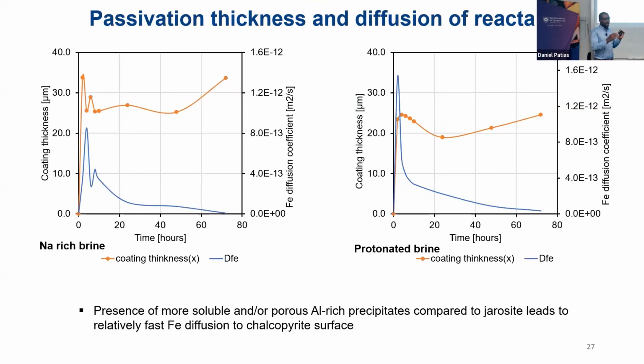Theoretically, we wanted to understand, okay, if we form a precipitate and we're able to predict its thickness and relate it to the diffusion rate of, say, your ferric in solution, what then is the effect comparing your sodium chloride and your protonated brine? In the case of sodium chloride rich, we predicted the thickness of jarosite to be around 35 microns, and with that, you have a decline in your Fe diffusion coefficient with time. Whereas in the protonated brine, even though we're getting the thickness around 25, what is forming is sort of soluble and porous. So you could still get your Fe diffusion coefficient very high, 1.6 E minus 12 meters squared per second.